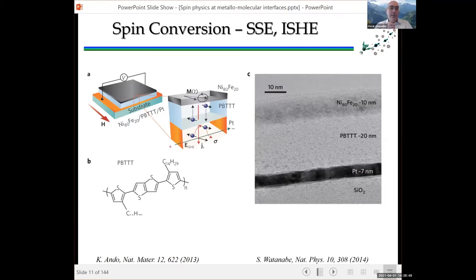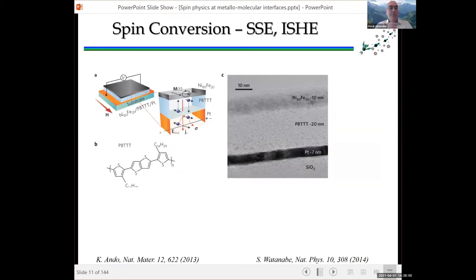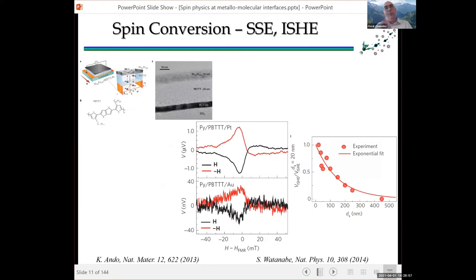And then what you can see is that as you generate this resonance, ferromagnetic resonance, and you inject this spin current, if you put together a heavy metal with a large spin orbit coupling with your polymer material, the polymer has a very small spin orbit coupling, but in this case, a very large mobility. Then you put a heavy metal on the other end. The heavy metal is going to split the currents in different directions. And because of the different chemical potentials for spin up or spin down, that is going to translate into a voltage that you can measure, the inverse spin Hall effect. But in this case, measured through a molecular layer.